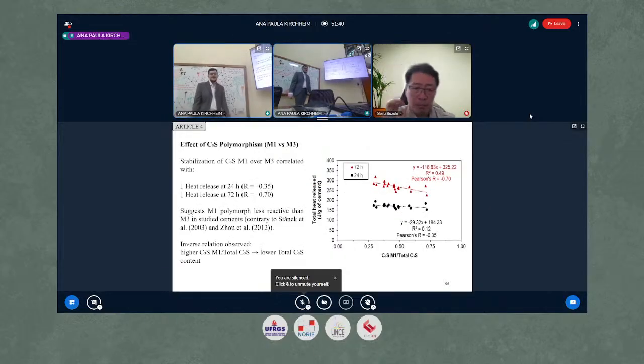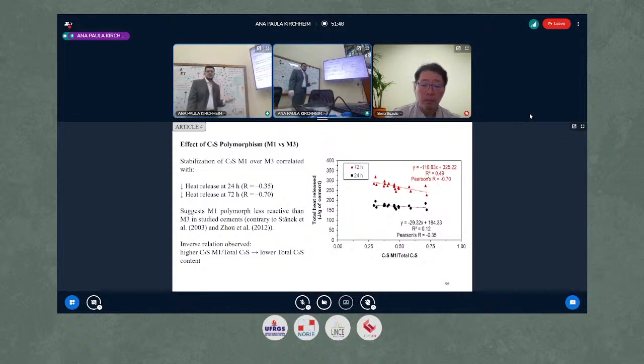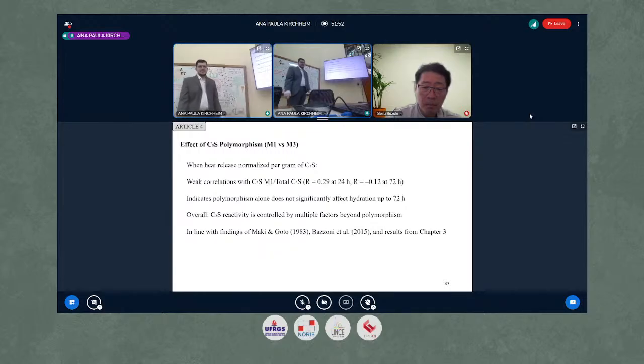Here I see the correlation of the properties that I calculated with each clinker. I highlight here again the influence of alkali in the initial reactivity of clinker. The alkali influenced a lot the first days of hydration. We didn't observe an influence of C3S polymorphs, neither in calorimetry nor in strength. C3S M1 was not more reactive than C3S M3. In fact, when you have more C3S M1, you usually have less alite, less C3S. So the clinker was less reactive if you take it globally. But we didn't see a greater reactivity of C3S M3 or M1.